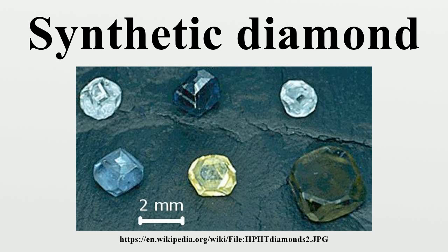The De Beers Diamond Research Laboratory has grown stones of up to 25 carats for research purposes. Stable HPHT conditions were kept for 6 weeks to grow high-quality diamonds of this size. For economic reasons, the growth of most synthetic diamonds is terminated when they reach a mass of 1 carat to 1.5 carats.